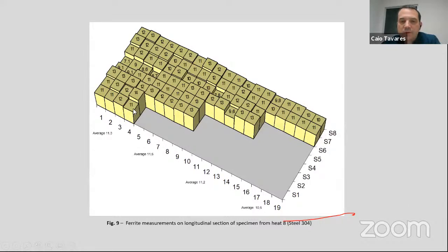So these maps show how we measure the ferrite on this sample. The sample was sectioned in the middle, the longitudinal direction, and we divided the samples in small squares, and we measured the ferrite in each one of those points. So we came here in each one of those points with the probe, and we measured the ferrite content. So here is the distribution of the ferrite in different thickness of the sample. So, and those are the averages of ferrite that we got.